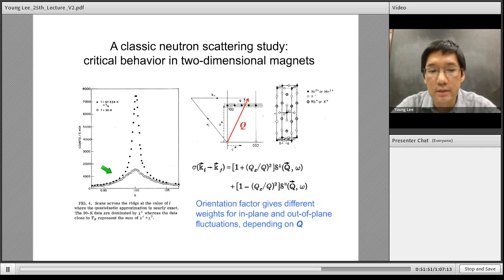For the black filled symbols, you have this divergence due to the longitudinal part that's along this Ising easy axis direction. But as you cool down below TN, that susceptibility should die off very quickly like a power law. And when you're at 90 Kelvin, you're just left with the transverse fluctuations.